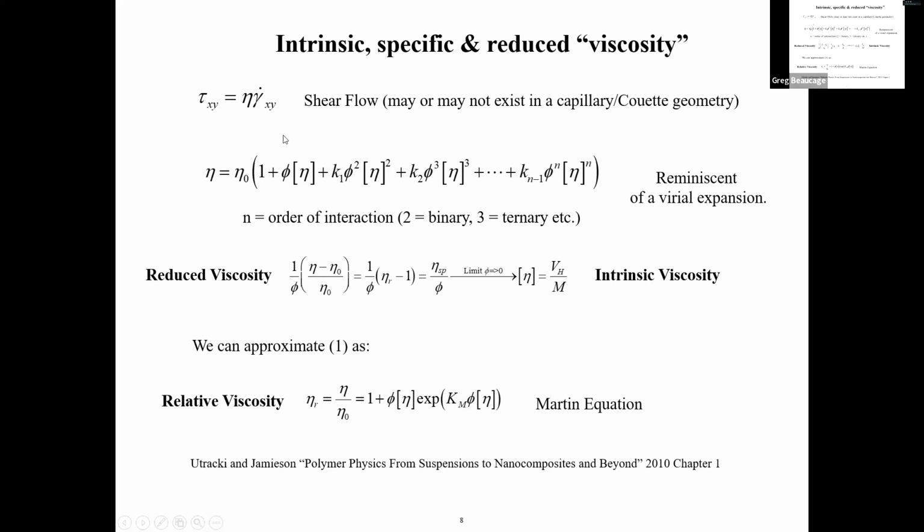So in a virial expansion, we're dealing with the osmotic pressure, and then we do a concentration series, and you get these prefactors. So you think, well, these prefactors must have something to do with intrinsic viscosity, especially because the second virial coefficient is the excluded volume of the thing, which is the same thing as this, right? In other words, this is kind of the excluded volume of one coil. So it starts to look like this is the same thing as a virial expansion with osmotic pressure, because B2 is an effective volume, and then this thing is kind of a volume per, right?